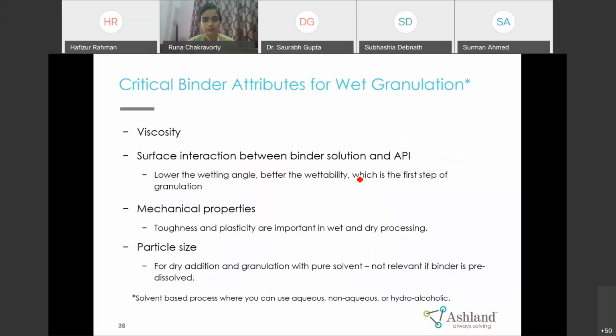Coming to wet granulation, it is different from dry processing, because here viscosity of the binder solution is very important, very critical. It should not be too viscous, so that you may not be able to pour it properly in the dry mix during granulation, and it will not be able to hydrate the blend if its viscosity is too high. And then surface tension, surface interaction, that is also very critical. If it is not proper, then it will not bind with the blend. And then mechanical properties, toughness, plasticity, these are also very critical.